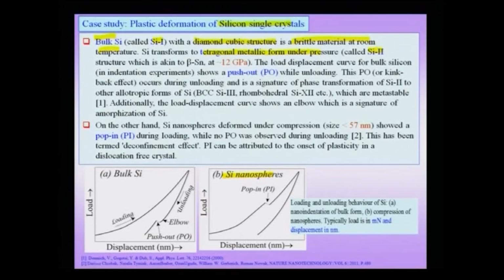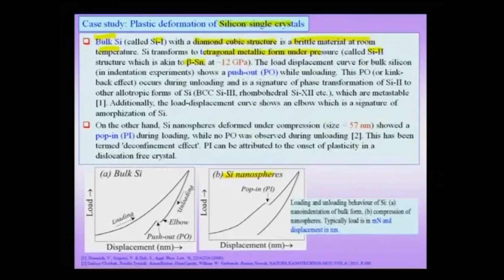This metallic form of silicon is similar to the beta tin structure, and we know that tin also is found in alpha tin and beta tin forms. Not only is there a crystal structure transformation when it goes from alpha to beta, but there is also a change in the metallic character when alpha tin goes to beta tin. And this transformation in the case of silicon actually occurs at a very high pressure of about 12 GPa.